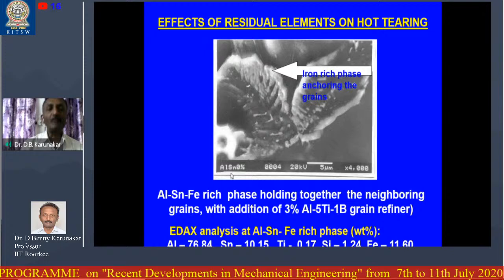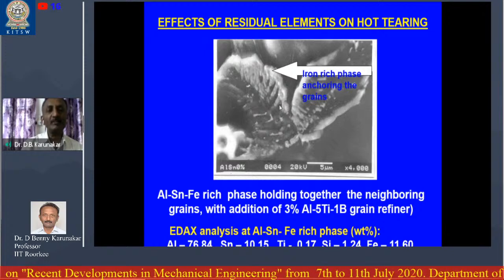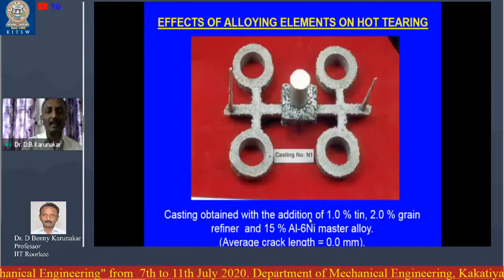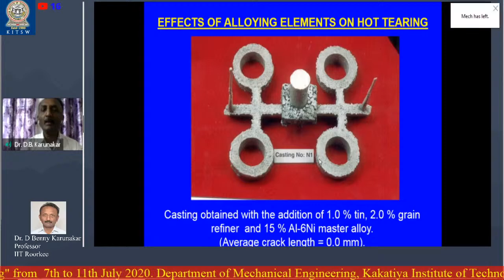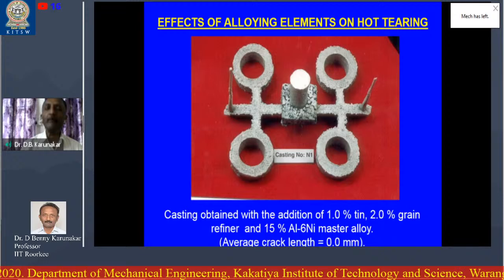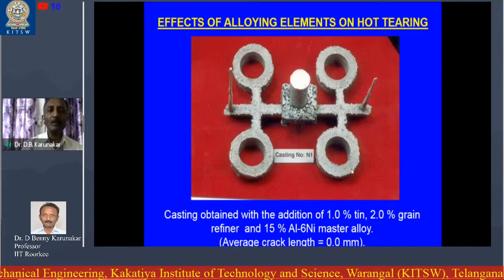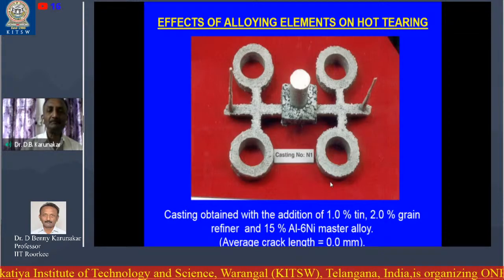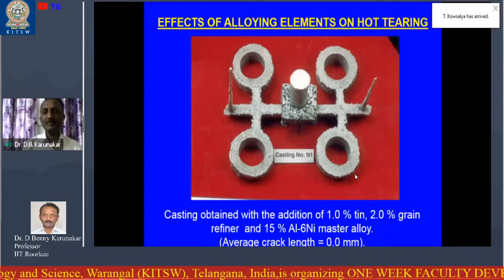Similarly, another investigation we have made. We added nickel to the aluminum 1% tin alloy. When we added nickel, again there was no hot tearing. We investigated why, with the addition of nickel, the hot tearing had completely gone.